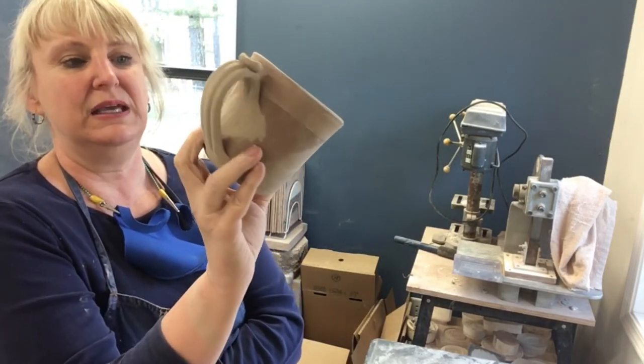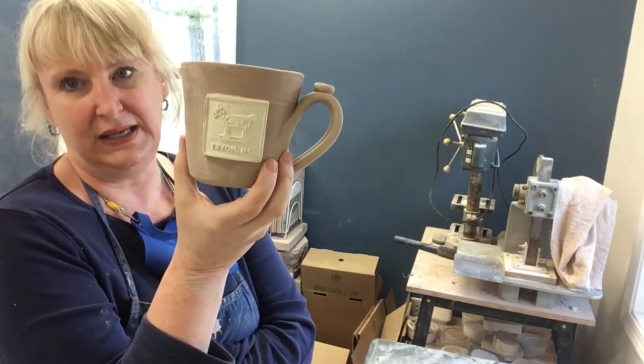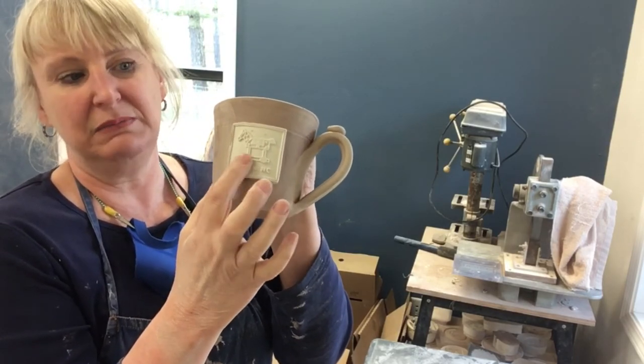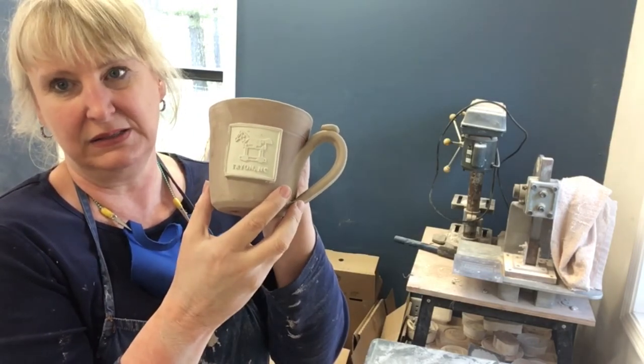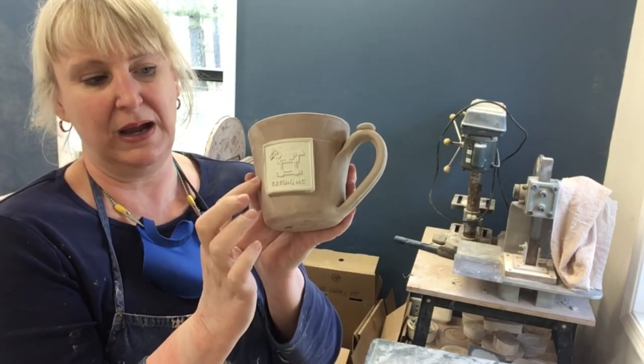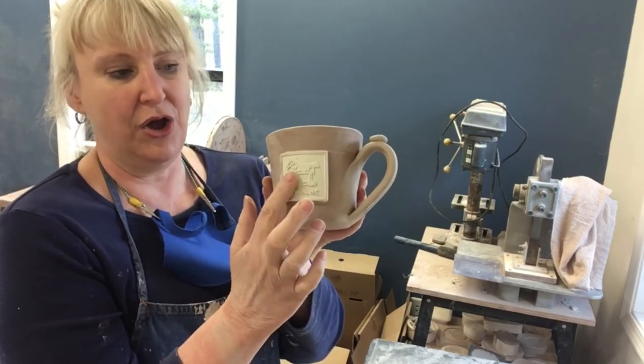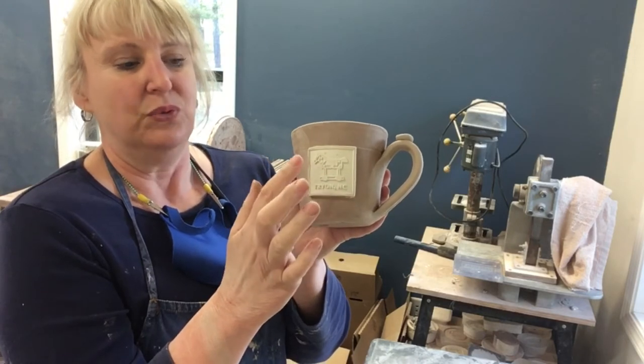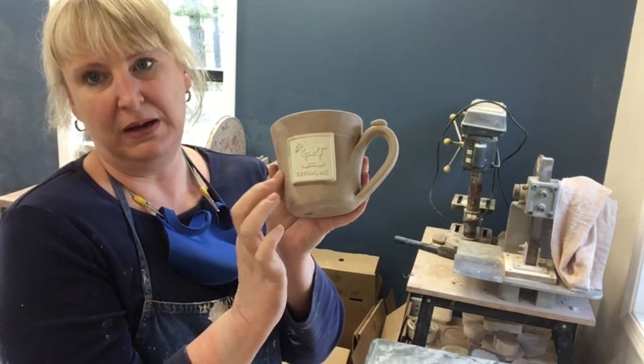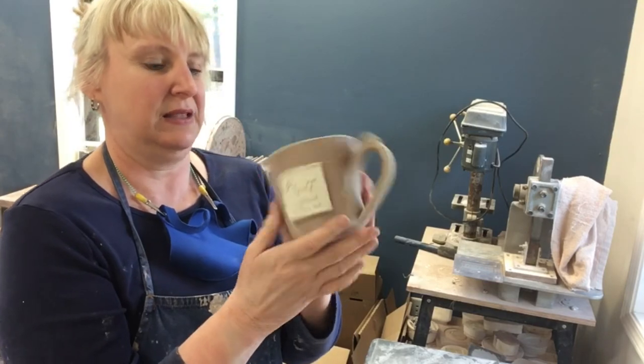The other thing you might notice is that we have a brown clay body mug and a white clay body medallion. So when we glaze these, the glaze looks different on the mug compared to the medallion — it's slight, but it makes the medallion be the focal point of the piece. There is a little bit different shrinkage rate between the white clay and the brown clay; the white clay actually shrinks a little bit more. So when we put the white clay over the curves, we try to get the medallion a little bit stiffer than the mug if possible, and that way we get a better fit. We'll use either color of slip — sometimes white slip underneath, sometimes brown — and it doesn't seem to make that much of a difference.